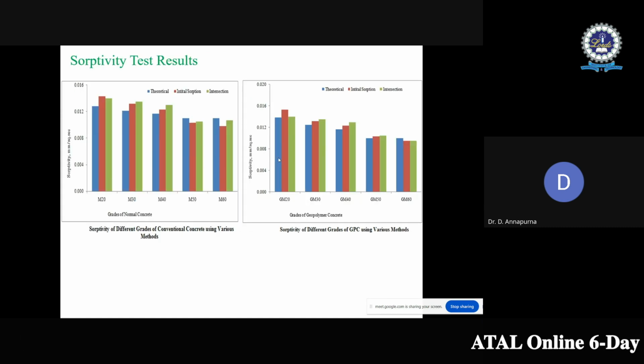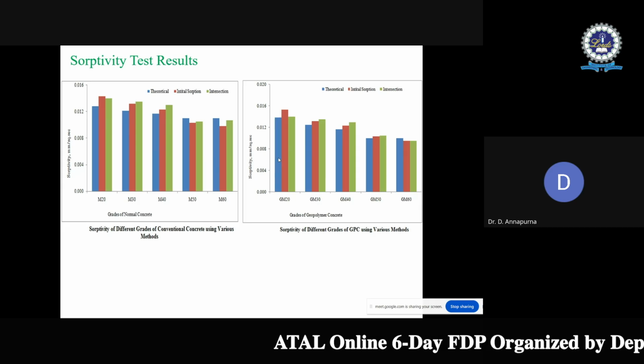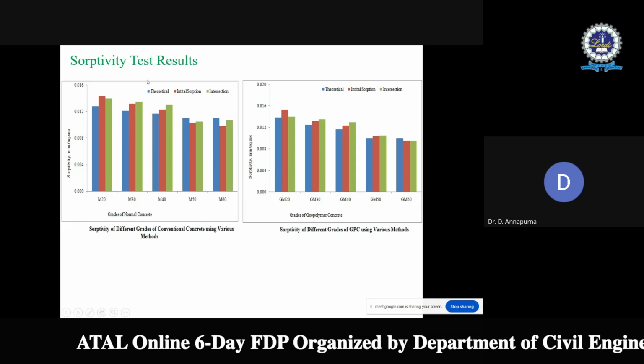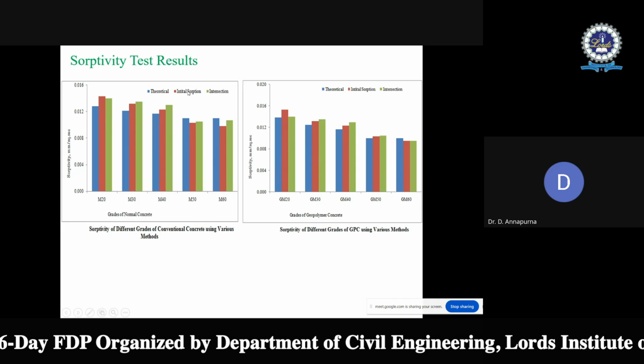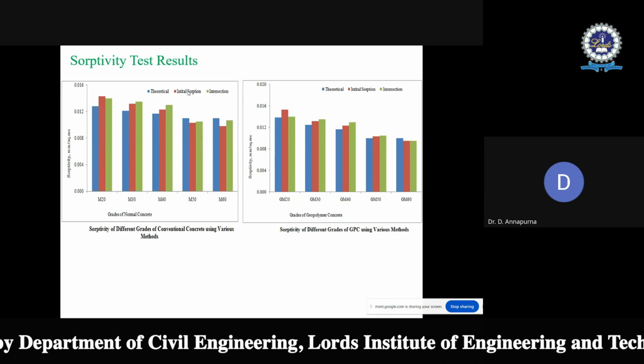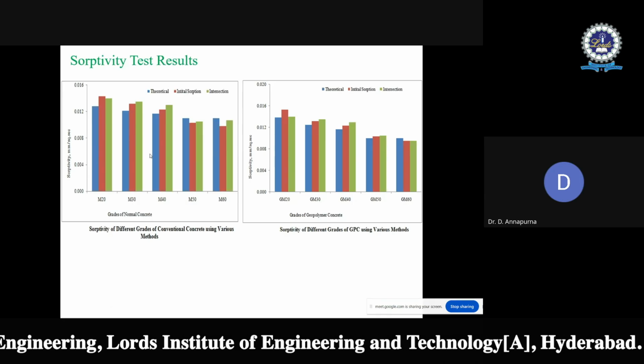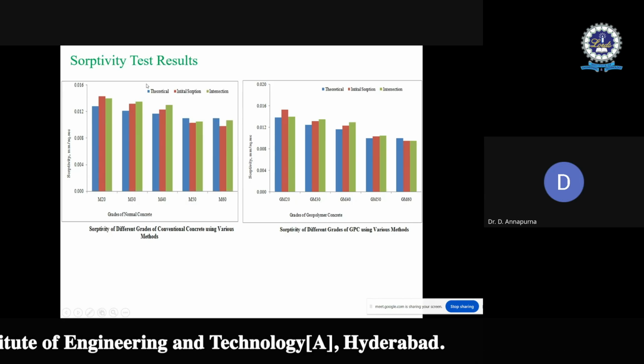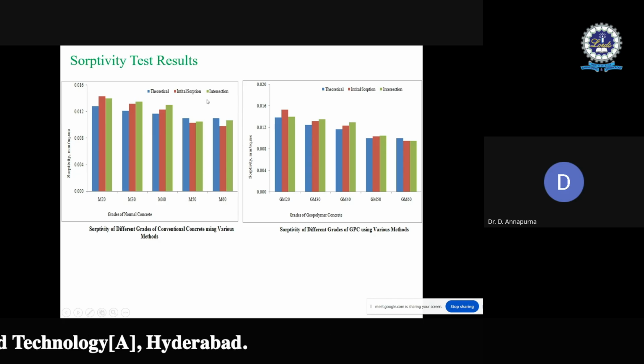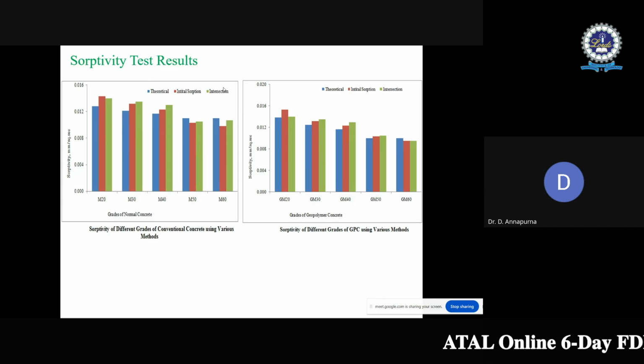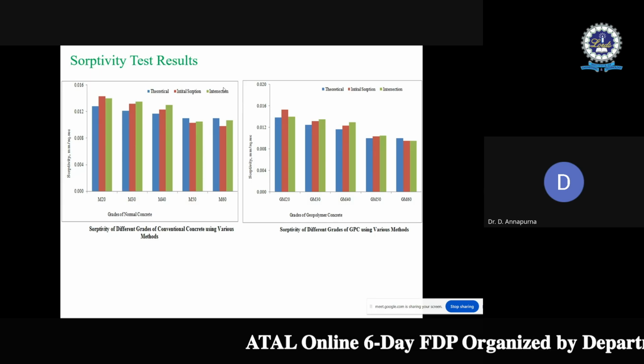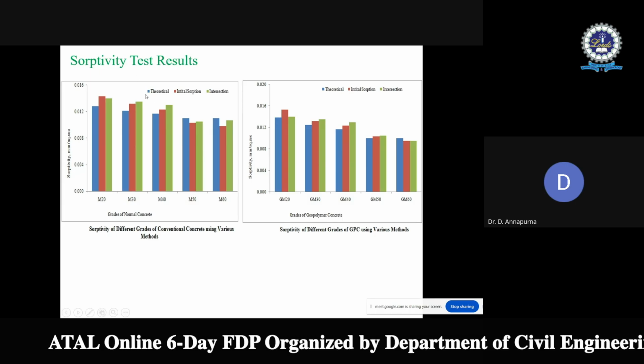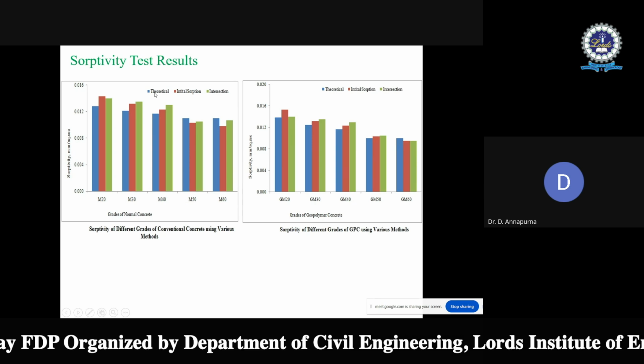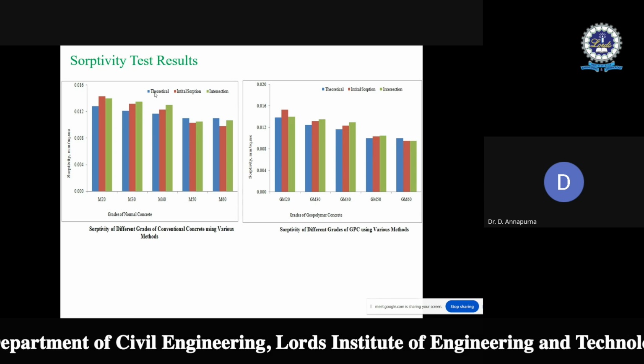Then the sorptivity test. The sorptivity test is conducted as per the ASTM standards. Here the initial sorption is conducted for the first 6 hours. Then the final sorption. The intersection of the final sorption and initial sorption is considered. Final sorption, as per the code, should be conducted up to 7 days. So then you will get the final sorption value. Then the theoretical sorption, the equation specified by the code to get the sorptivity,